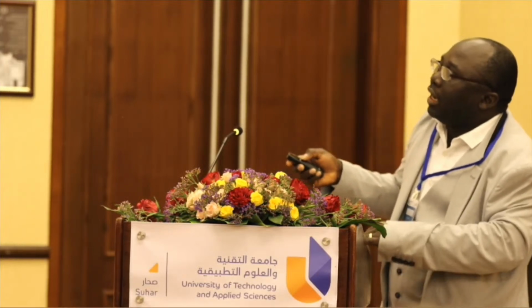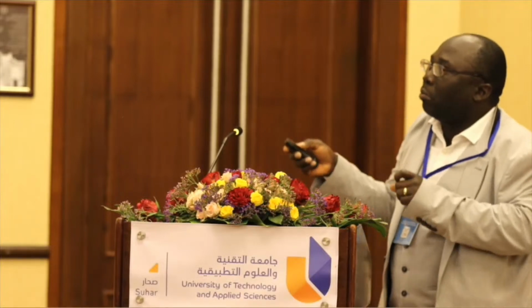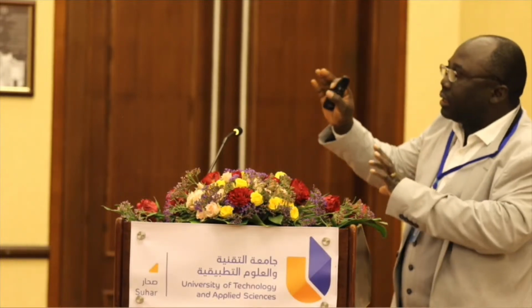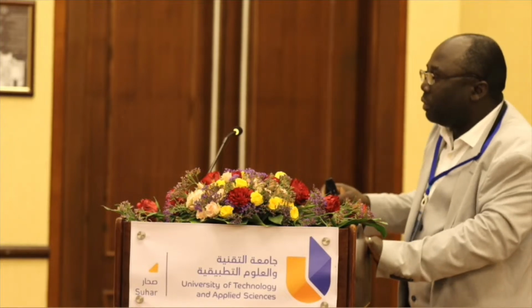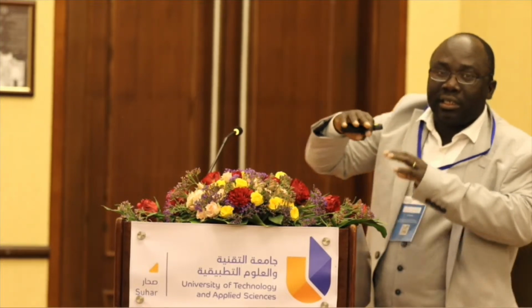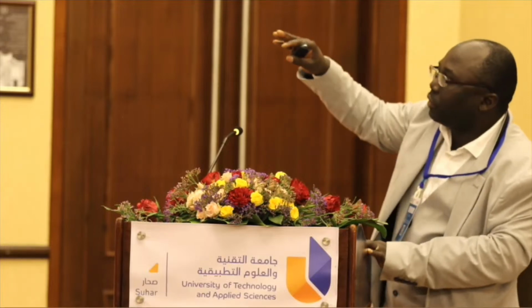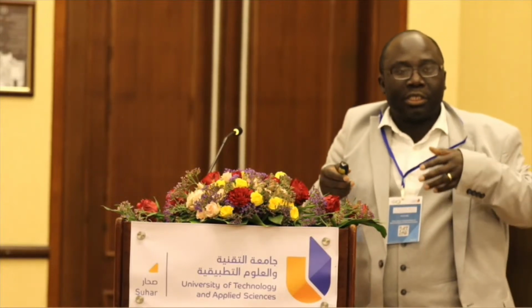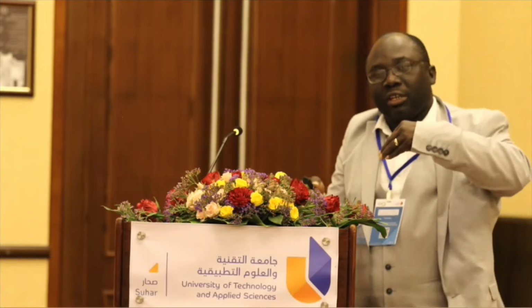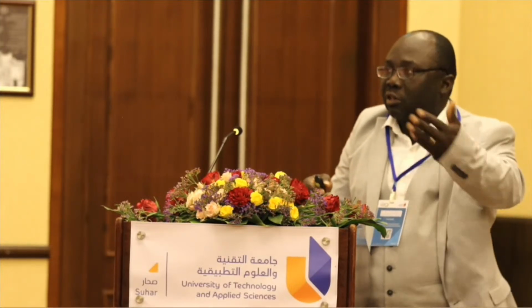All right, so initially we did some assessments, we did some models, and here is a result that we developed from the model, which highlights the existence of equilibrium limitation within the reactor. The problem with that is that it makes it very difficult to achieve, say, 90% conversion, for instance. In other words, 90% of the ammonia that you're putting into the reactor is converted, is completely decomposed. It's very, very difficult to achieve that when you are using tubular reactor design.